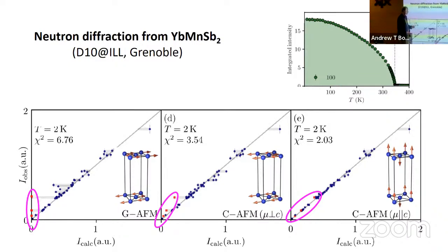They're sort of clustered because the intensity of these peaks depends upon the structure factor. That means the interference of the scattering from the particular structure. That's why they're sort of clustered like this. This one has a rather large error bar, so probably this is just experimental error that it's not fitting. This is probably about as good as you can get for this type of method. Thank you.